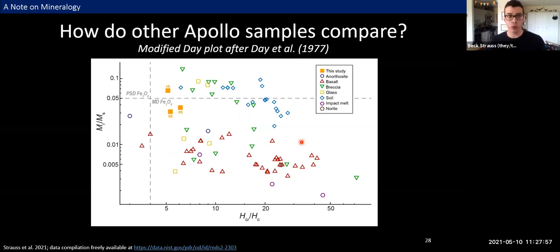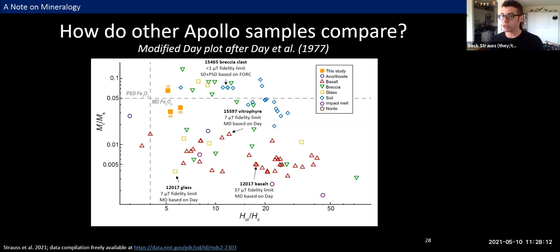So I've also included these gray dashed lines, which indicate domain state regions from the original Day plot that were often used to interpret grain size. I'll note the positions of samples from a few recent studies on this figure, just sort of by way of example, and you can kind of get a sense from this handful of points that the general trend that we're hoping for does seem to hold. We see better, lower fidelity limits as we move toward the upper left of the plot. However, there is a problem when we start to look at those domain states, which again are what grain sizes often get inferred from. And the problem is those dashed lines don't actually exist. Those guiding domain parameter ranges were originally developed for magnetite, Fe3O4.